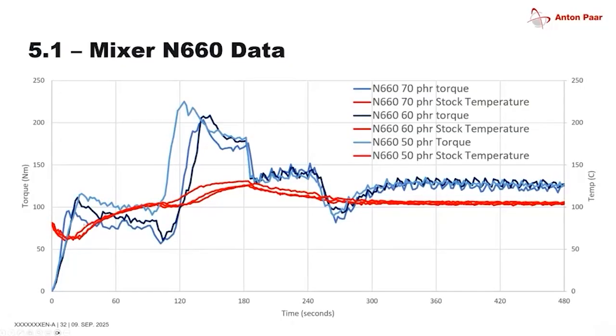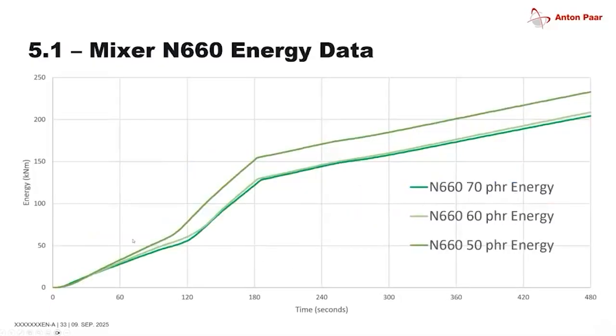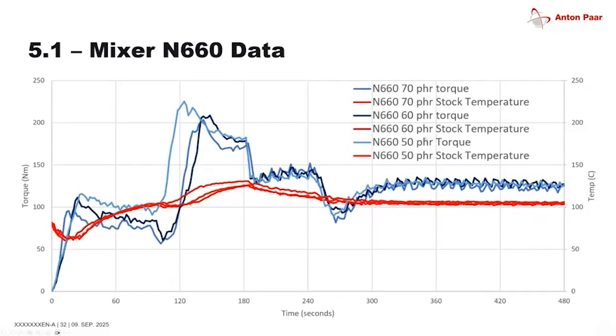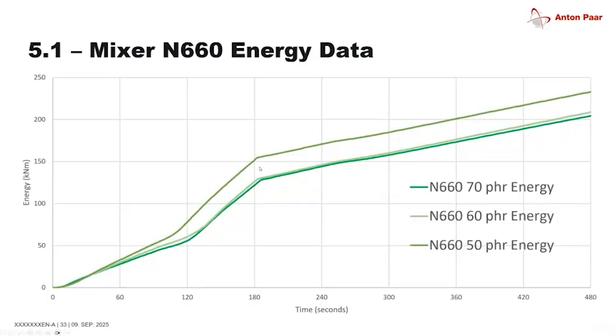Because for those of you that have not yet been familiar with torque rheometry, the area, so the integral under the torque curve, is your energy that you put in between 2 points of significance. If you then know your sample weight, you can also get the specific energy needed. Here, this is just visualizing this very nicely, how close the first two were, 60 and 70 PHR. Again, we have to be careful. No, sorry, the 50 PHR. We anticipated that the lab technician was a little ahead of time filling that. You will immediately see that because that literally translates here. There's no real reason why the lowest version has the highest energy in there.